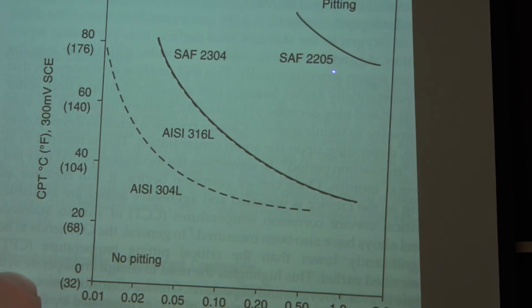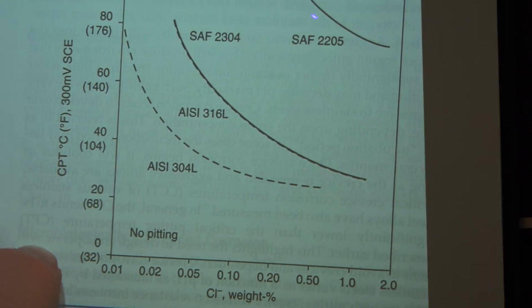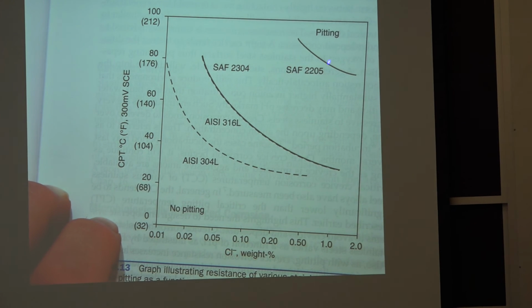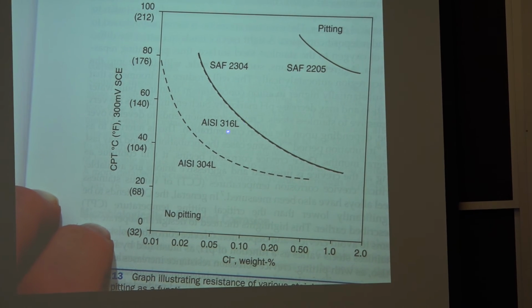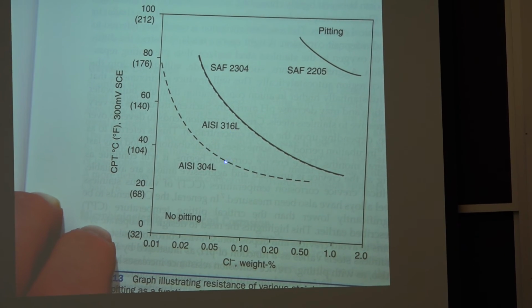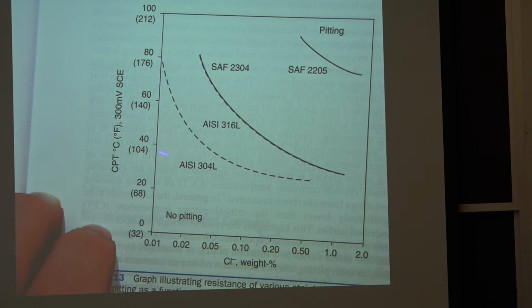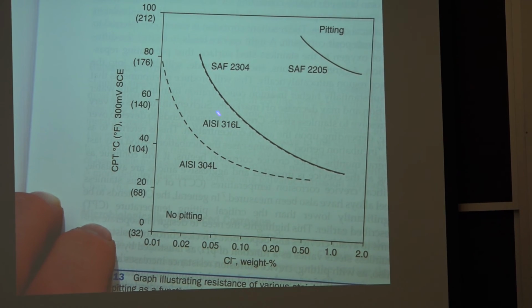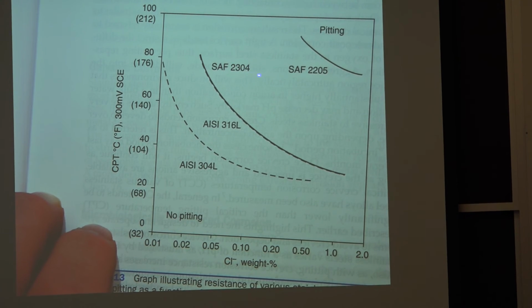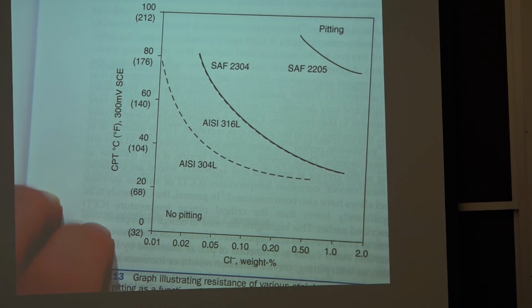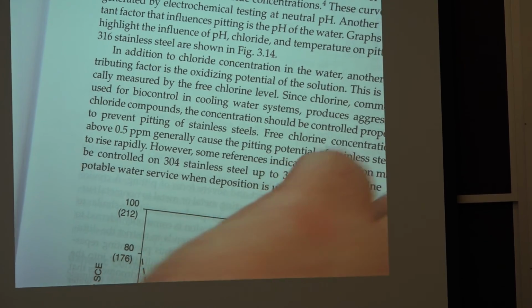This is 304, 316, 2205, and pitting. And so this is what we ended up using at the Miami Art Museum, significantly better than 316 or 304. This is, well, AISI 304 is down here, 316 is in here, and this is a 2304, which I don't even know what it is, and a 2205.